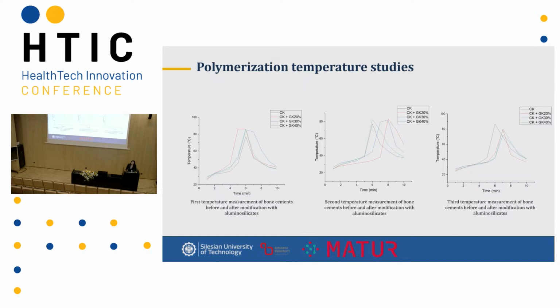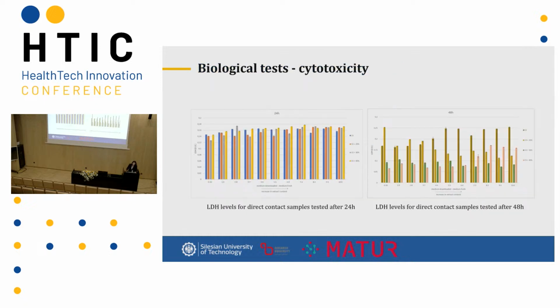But newest research says that during endoprosthesis surgery, when the bone cement is polymerizing, the surface of the implant is heating. This is a good thing because it can destroy the biofilm and help in therapy for the patient. I also checked the biological tests, the cytotoxicity. I used LDH experiments. After 48 hours, the amount of 30-40% is the excellent version for the next experiments.